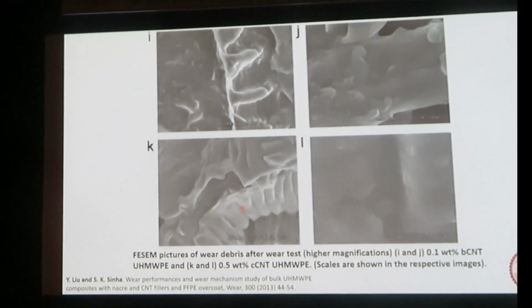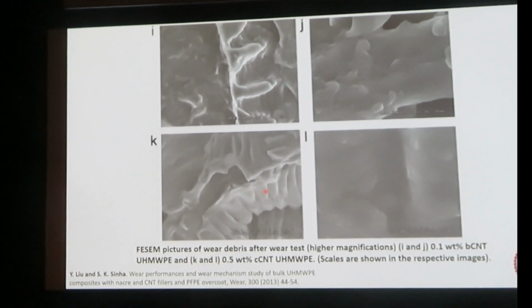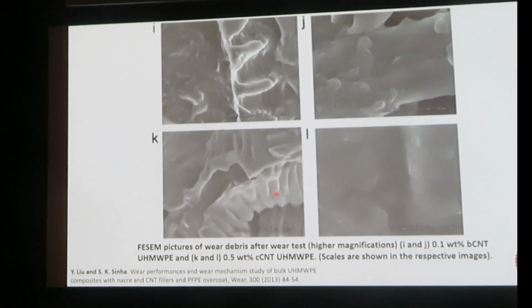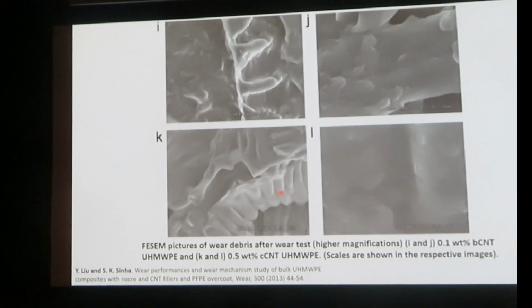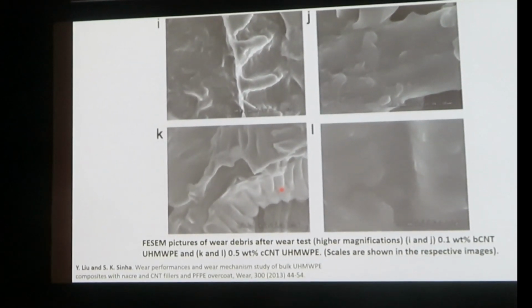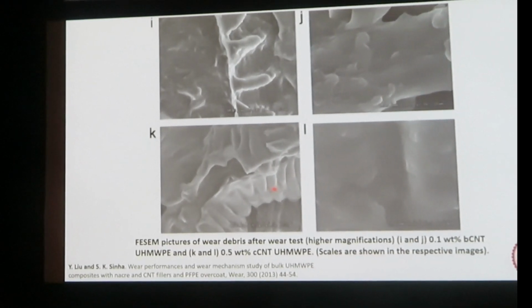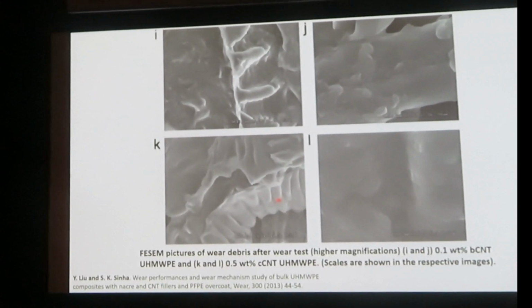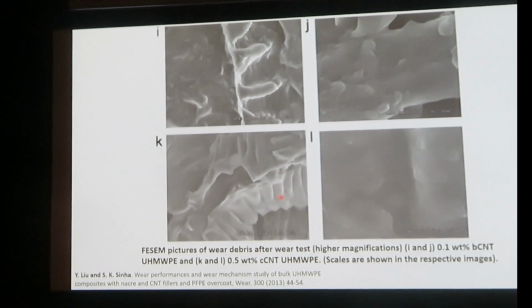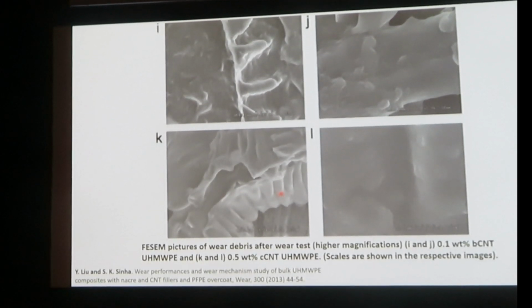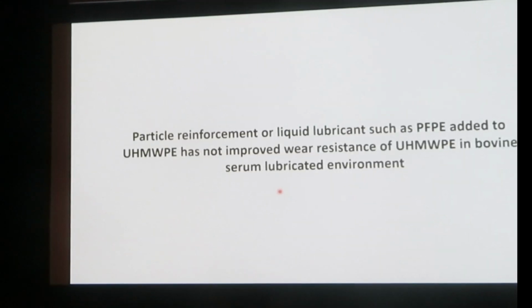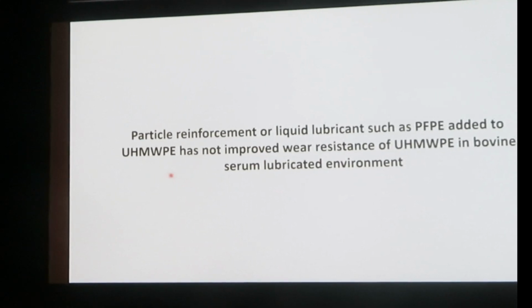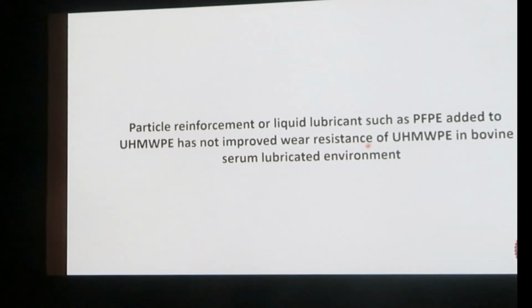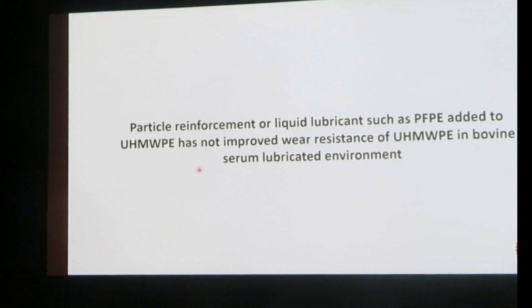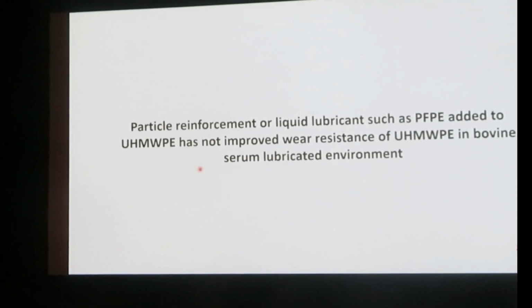These pictures basically show at very high magnification how UHMWPE actually deforms plastically, and the good thing about UHMWPE is that it is very plastically deformable. It doesn't allow any cracks to grow, and that is the reason why it is so wear resistant. So the conclusion from this review was that particle reinforcement or liquid lubricants such as PFPE added to UHMWPE has not improved the wear resistance.